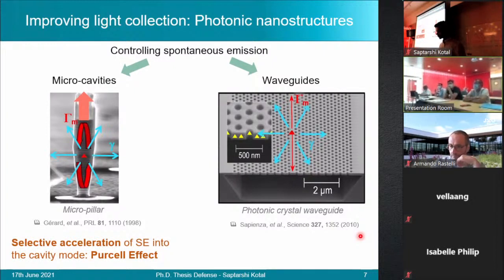In accelerating the spontaneous emission, it of course makes it less sensitive to the sources of noise around the quantum dot, but at the same time, it results in a very narrow operation bandwidth. Waveguides, on the other hand, make the guided mode the preferential emission channel. And they do so by suppressing the spontaneous emission in all unguided modes.